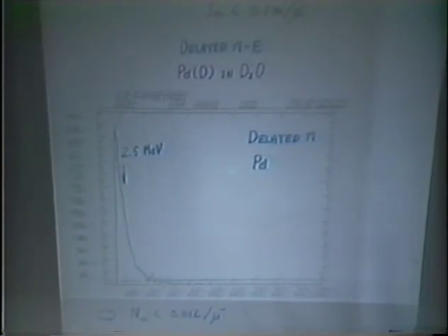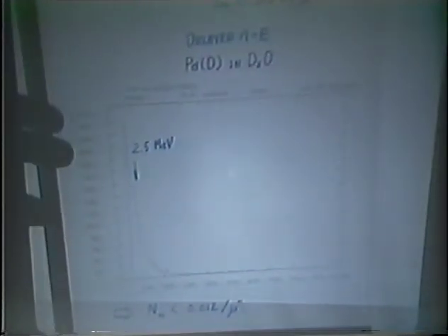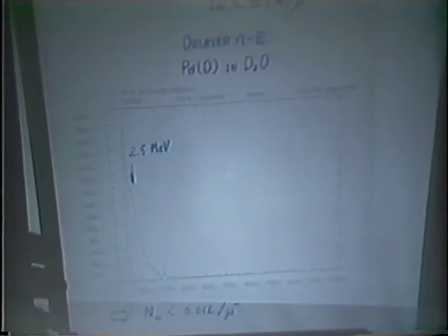Then we switch to the search for fusion neutrons. This is n-gamma discrimination, and this is the neutron time spectrum, mainly for the neutron events related to the palladium. And this is the delayed neutron energy spectrum for the pure palladium, and this is the delayed neutron spectrum for the palladium D in D2O, and essentially no change, particularly around the 2.5 MeV peak. After analyzing this data, we concluded the fusion neutron yield is below 1.2%, sorry, 0.012 per mu minus.